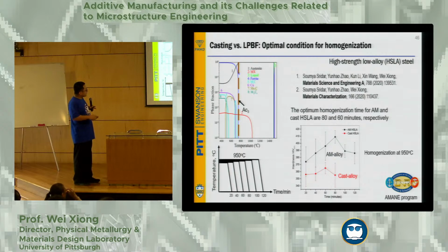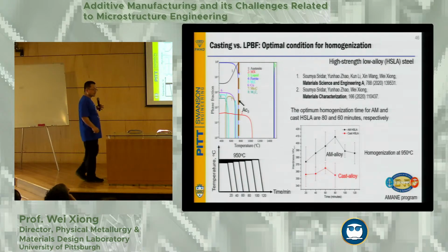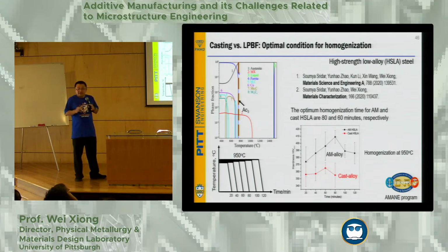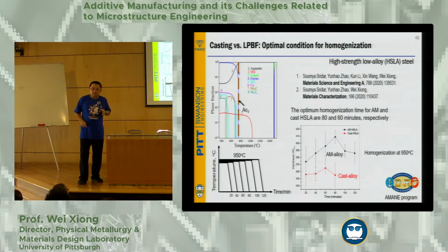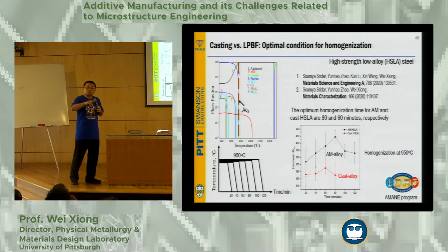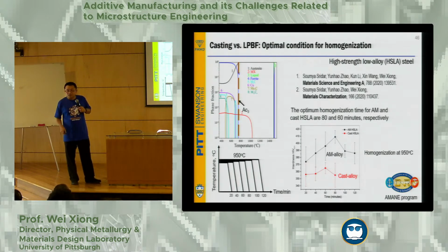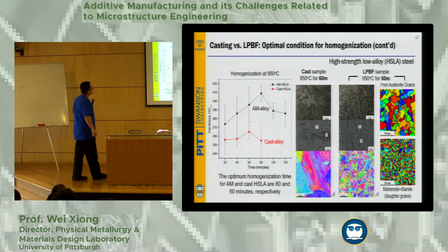Because if you simply look at the homogenization for the AM alloy, they're actually showing different behavior during the homogenization. The amount of bainite and martensite in the as-cast status is quite different from the additive manufacturing. So you will no longer be able to use the traditional processing parameters to process the additive manufacturing component. That's very important.